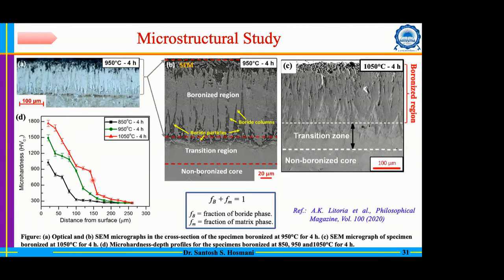Okay, so the bottom line is that, in principle, you have a mixture of boride as well as matrix, and the fraction of boride plus the fraction of matrix is equal to 1. That simple concept we have adopted here from this particular slide. And in this transition zone, you can see very tiny boride particles in this micrograph. These tiny boride particles are forming along the grain boundaries as well as in the matrix.